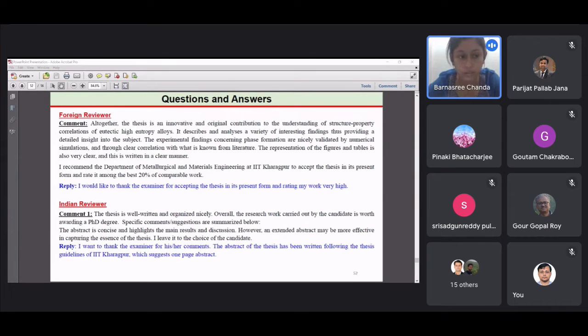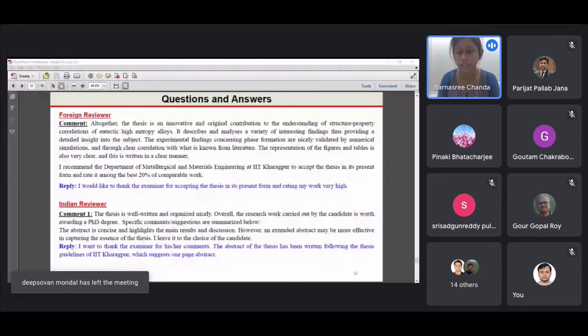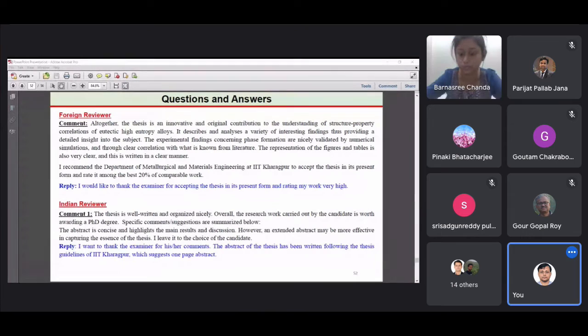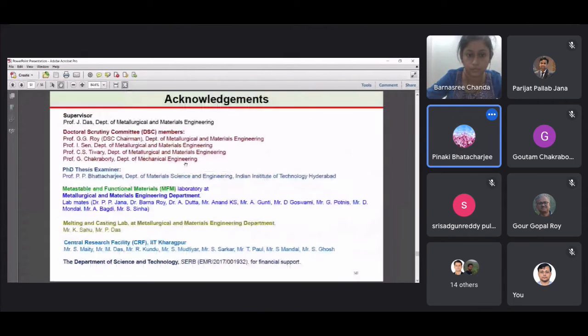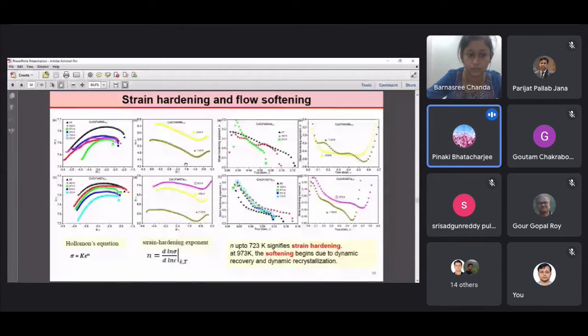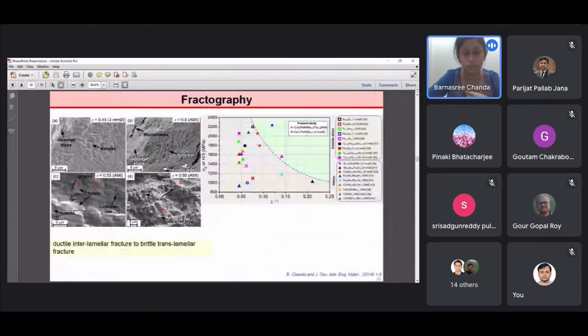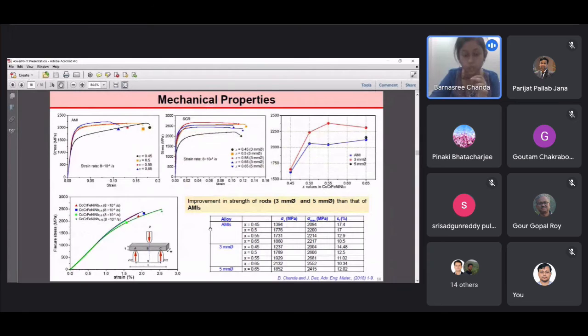In 2016, when we started working, the alloy composition you have talked about, aluminum, cobalt, chromium, iron, nickel 2.1, was proposed in 2014 by Lu et al. That is the first time the term eutectic high entropy alloys was used. So in 2016, we thought of proposing a new class of eutectic high entropy alloys. Therefore, we prepared this alloy system, and we have not performed tensile tests because our samples are very small, so we had a problem while gripping. For your eutectic alloy, which is FCC plus BCC, FCC plus Laves phase particularly, did you carry out your tensile test? No, sir. Due to the limitation of the sample size and the gripping problem, we were not able to do the tensile test. Therefore, we have moved to the 3-point bend test.